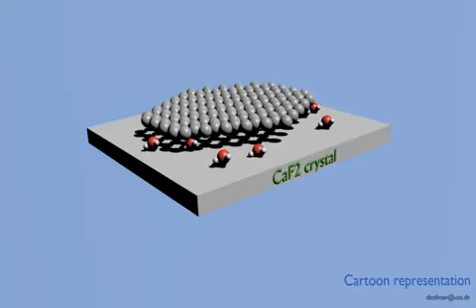Transport of water from the calcium fluoride surface underneath the graphene results due to capillary forces and explains the obtained images.